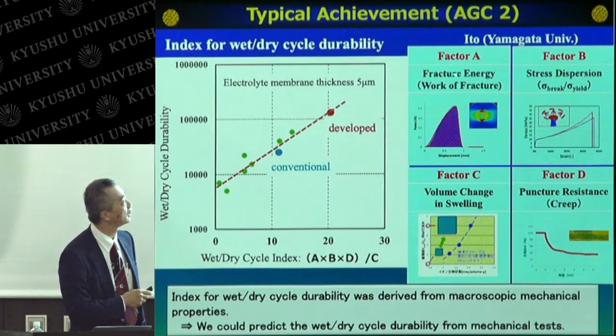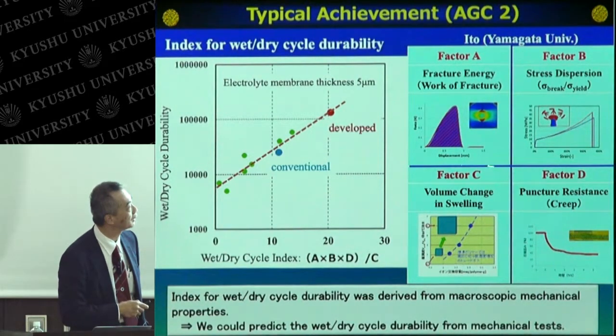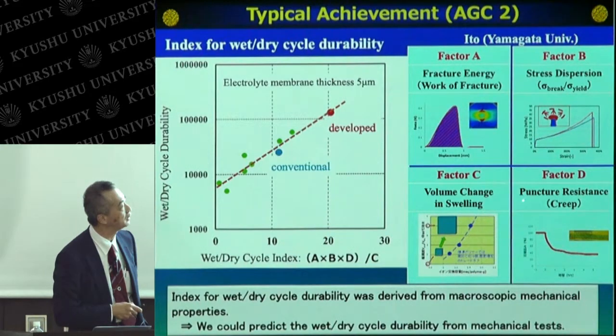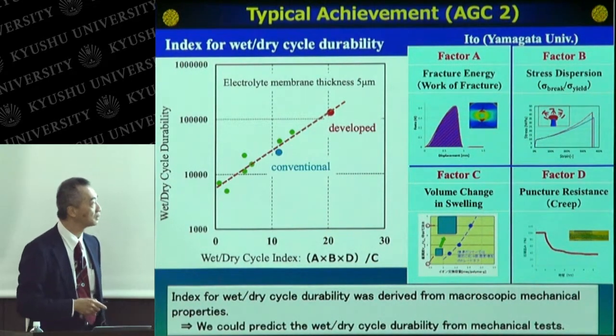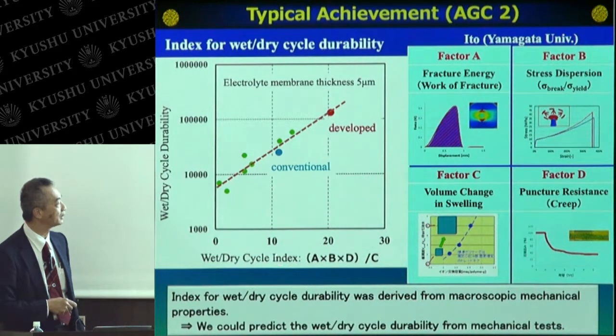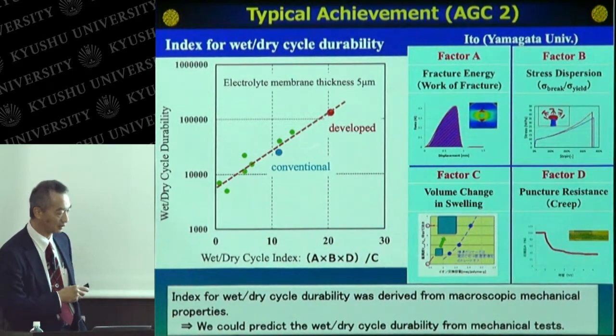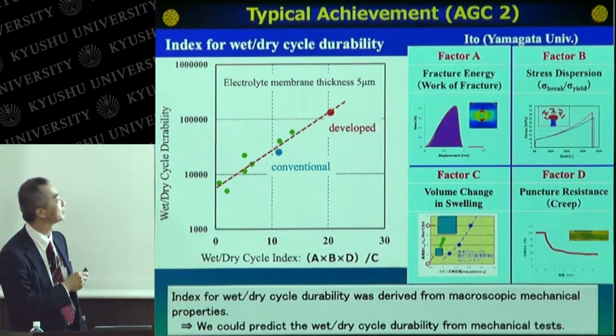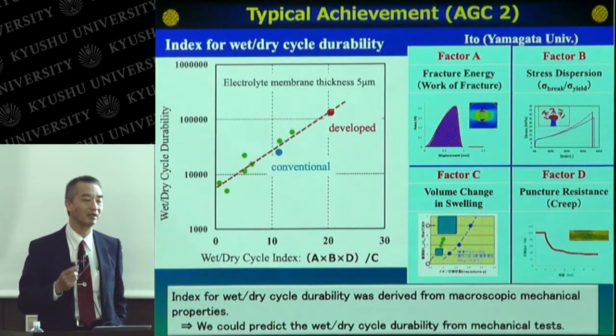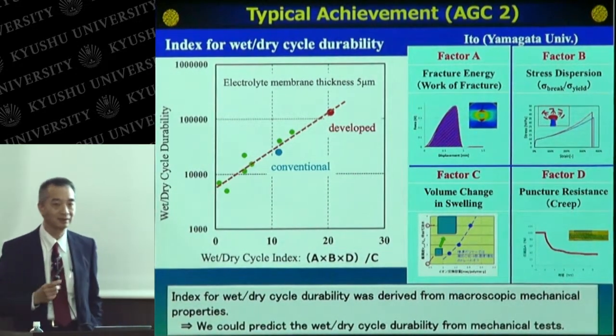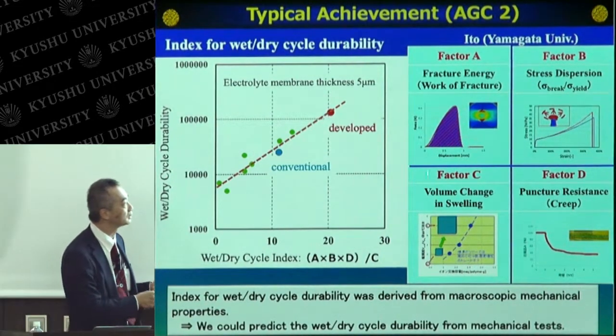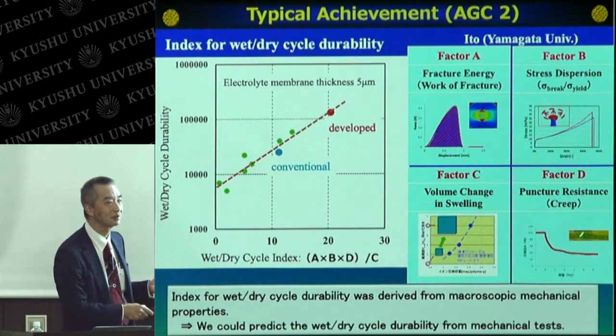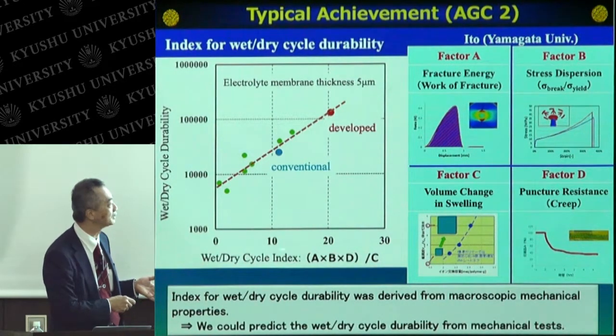So this index consists of 4 factors. Factor A is the fracture energy, factor B is the stress dispersion, factor C is the volume change in swelling, and factor D is the puncture resistance test, the creep test. So they combined these tests and obtained this new wet-dry cycle index. This index is closely correlated with the wet-dry cycle durability test. Usually it takes a very long time, about a couple of months, to check the durability, but when they use only these 2 experiments, in a couple of days, they obtained this index.